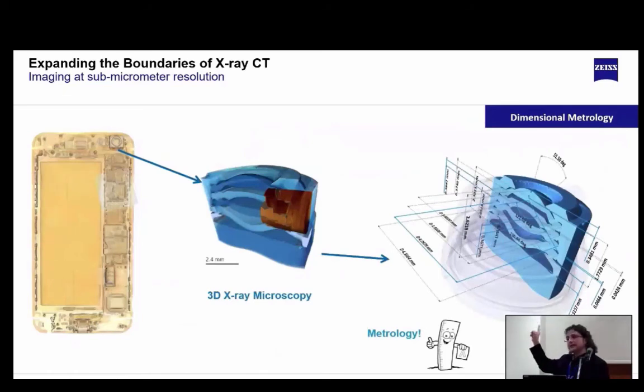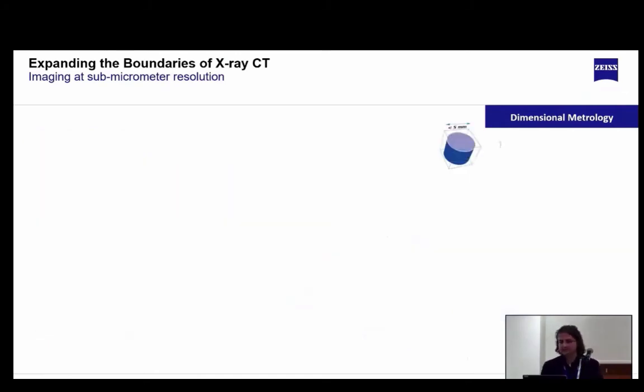This is something that you could not do with an optical measurement system or a tactile system, because you cannot get inside of the sample. The X-ray is the only way to do it without sectioning the part. And we can do that now, not only with high resolution, but high precision metrology, because we have this accuracy statement. And the typical measurements of interest are, of course, the lenses, the fixed annular wedges, centrations, diameters, gaps, lens-to-lens tilt, apex height, centrations, etc.